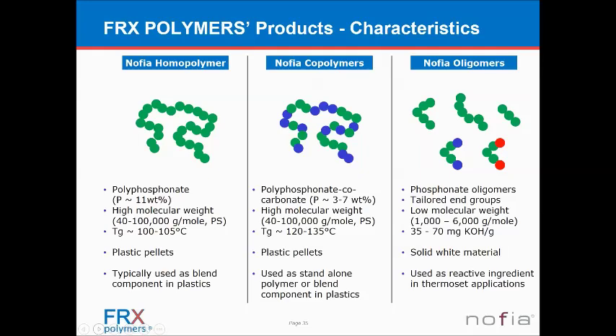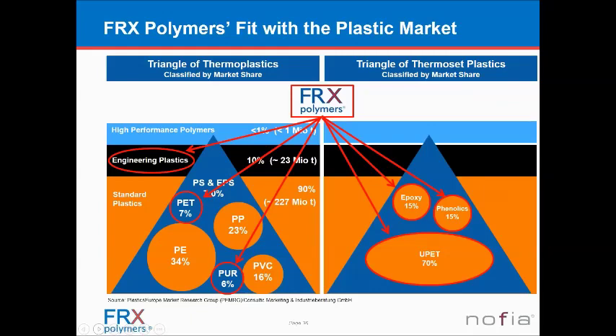And finally, we have the oligomers, which are small molecular weight versions of the first two materials. And because of the chemistry that we use, we can actually modify the end groups of these oligomers and make them suitable as reactive materials with other monomers. So these actually can be built into especially thermoset applications. So you can think of epoxy materials where they react with the epichlorohydrins. You can react them with isocyanates and therefore build them into polyurethane foams. So there's a lot of different possibilities that you can have with these reactive oligomers.